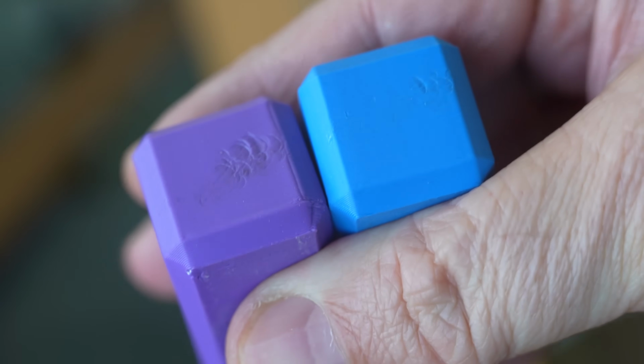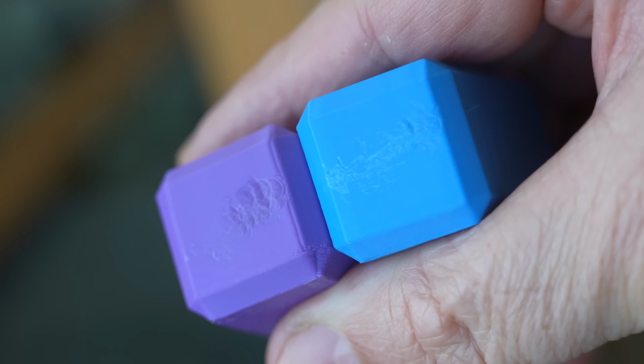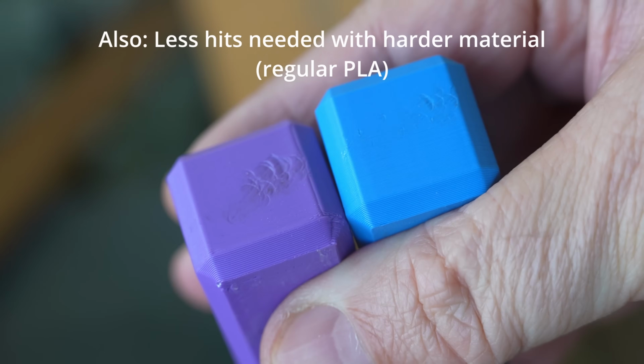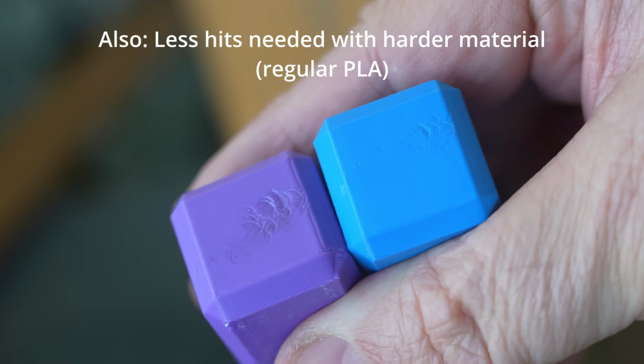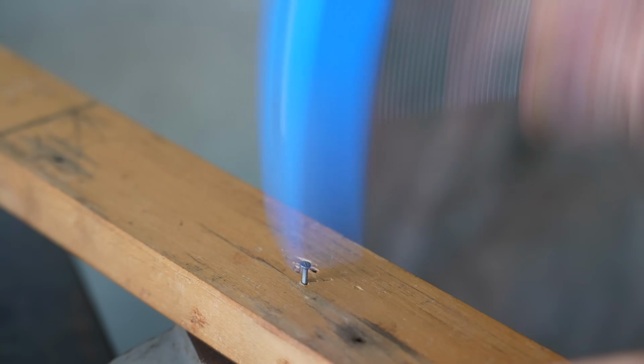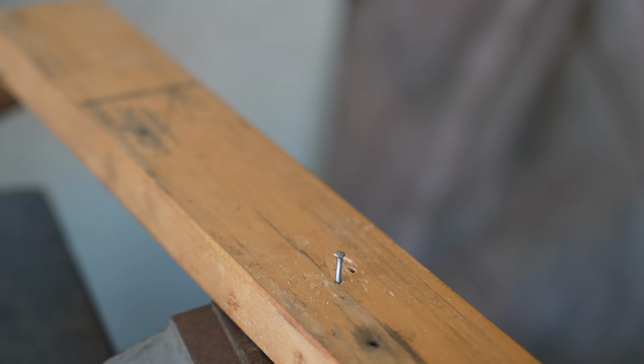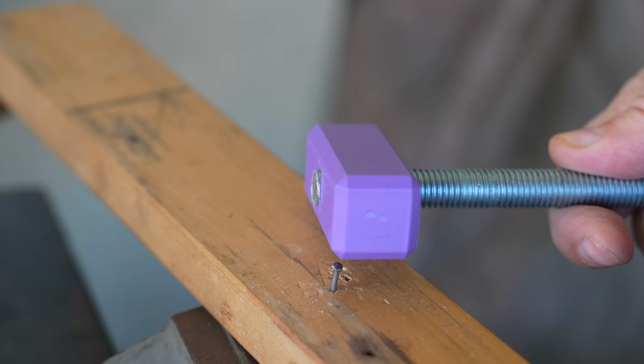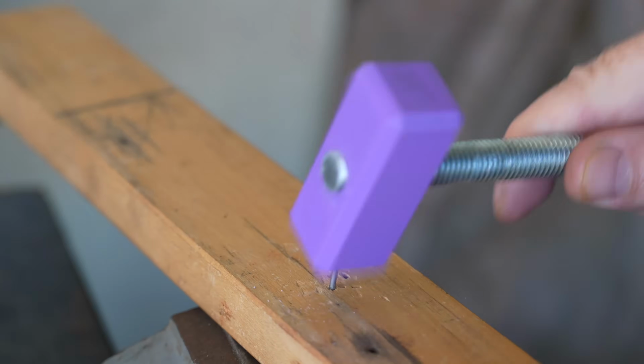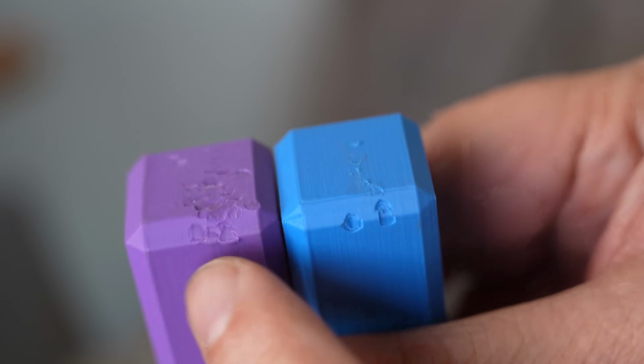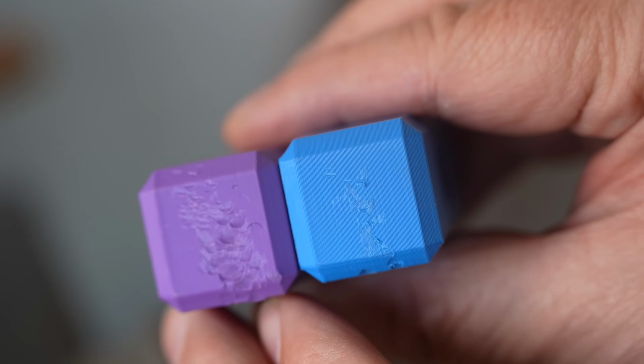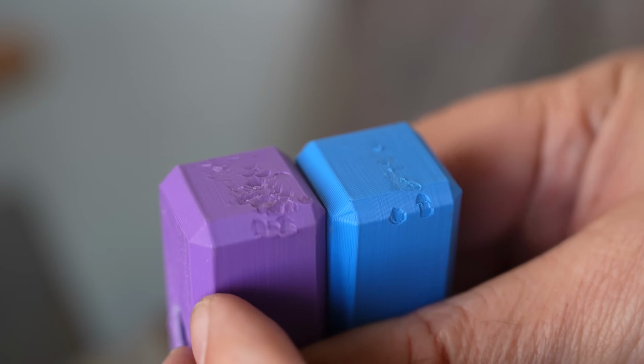At first look, more damage on the Super PLA Plus because it is tougher but looks like not harder, which is resistance of the material to the penetration. But when I was playing a little bit more with these hammers and I had a few hits with the edge, the damage of the Super PLA Plus was smaller. Maybe because of the toughness or maybe because of better layer adhesion, I'm not sure, but anyway, it was interesting testing.